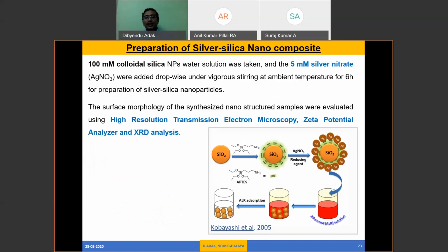So how have we done it? We added 100 millimolar colloidal nanosilica to a 5 millimolar silver nitrate solution, and then mixed it on a magnetic stirrer for 6 hours. Then the silver-silica nanoparticle will be produced. As we know, silver is positively charged and SiO2 is negatively charged. So using the Stober method, we can prepare the silver-silica nanocomposite.